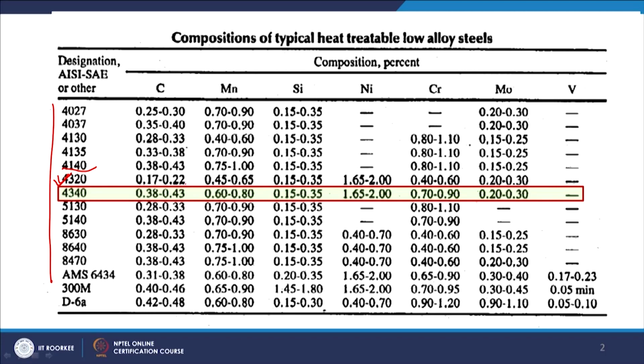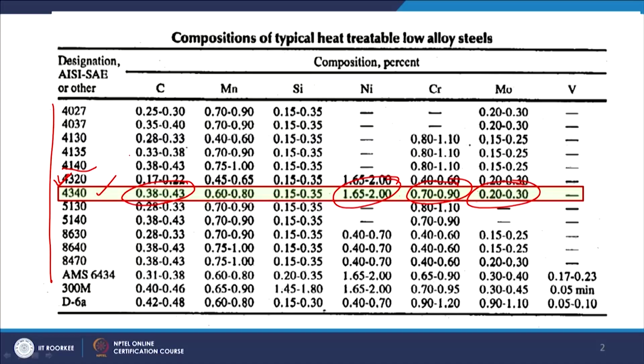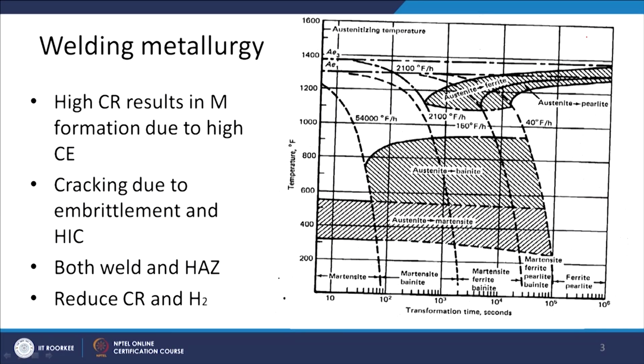So like say 4340 grade of the heat treatable low alloy steels has significantly higher percentage of the carbon, 0.38 to 0.43, so roughly 0.4% carbon. Chromium is 0.8% on an average, and 0.25% molybdenum, and nickel is 1.65 to 2%. So high concentration of these alloying elements in this typical grade of the steel will be leading to the higher carbon equivalent, so increased tendency for the martensitic transformation.